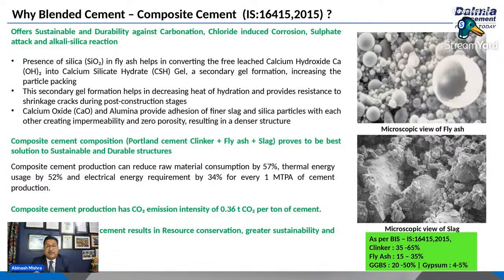This composite cement is only 4 to 5 years old in this country. Before 4 years or so, a code came into practice. Nobody is interested in using composite cement, thinking that it might result in poor early strength or later age strength. But believe me, we will show you certain cases where we have used composite cement with the required amount of high range water reducers and plasticizers, and we have found that it is better performing in later age strength or mid age strength in comparison to OPC plus fly ash or OPC plus GGBFS. We can also share live data in future. Next.